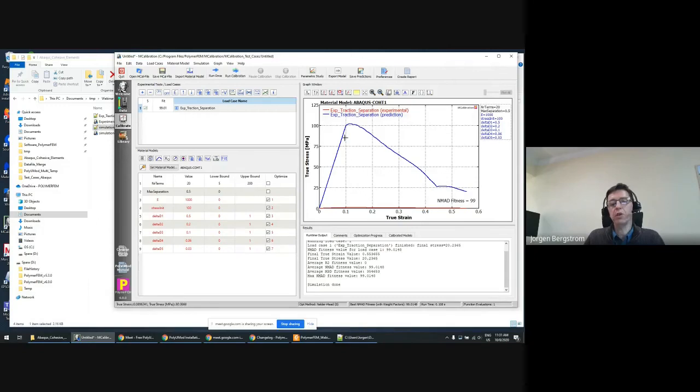We'll see that the modulus of this cohesive model that we have here is way too stiff. So I'm going to make it 100 times softer. So I'm going to make it 10 MPa. Stress initiation is where does this curve roll over? It's not 100 megapascal, it's about 1. So I'm going to make this 1. Then I run again. And that was pretty good.